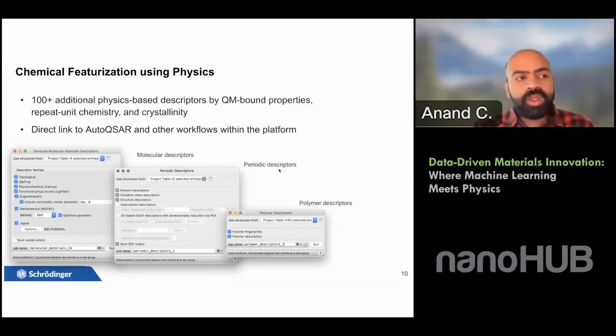Both AutoQSAR and DeepAutoQSAR are based on SMILES strings and 2D featurization schemes. But we know that for many cases and for many material classes, those 2D featurization techniques are not sufficient. So we can generate more types of descriptors. For example, we have a molecular materials descriptor panel, which can generate organometallic descriptors for different metal centers. You can specify the metal center and it can calculate properties like the buried volume, the bite angle and cone angle of those organometallic systems, optimized with DFT level accuracy.